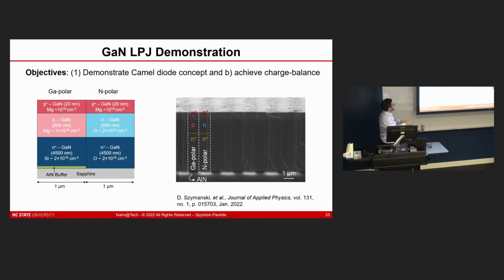In this case, the magnesium is incorporated during the epitaxy itself. And so we follow up with a lower temperature anneal to drive out hydrogen, which is very typical for MOCVD growth when you're trying to do P-type GaN. But we don't do an ultra-high pressure anneal. And so we don't expect there to be lateral diffusion or even, for that matter, significant diffusion as a result of annealing steps. You may have a sort of smeared profile of magnesium because of other things related to the growth step itself and magnesium being in the chamber and so on, but there's no anneal that we're doing to move the magnesium around after the structure is grown. Does that answer your question?